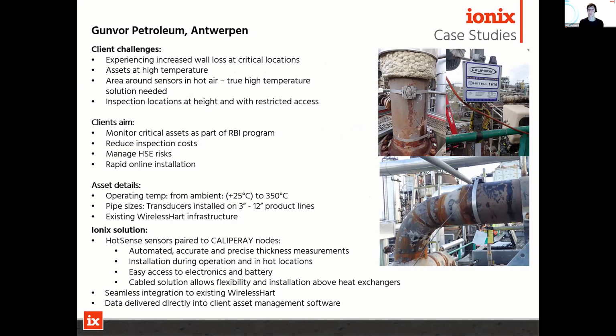Another quick example, this one is in Antwerp. Here they already had a wireless HART mesh network running a range of vibration and temperature sensors, and they just dropped some CALIPERAY in on site, automatically integrated with the mesh, and started sending data directly back to their control centers. Another key one is that they wanted to install some sensors above heat exchangers. The problem is that the actual ambient temperature above the heat exchangers was about 250 degrees C, so you couldn't install the electronics there. So the electronics were installed nearby with lower ambient temperatures, another key benefit of the system.